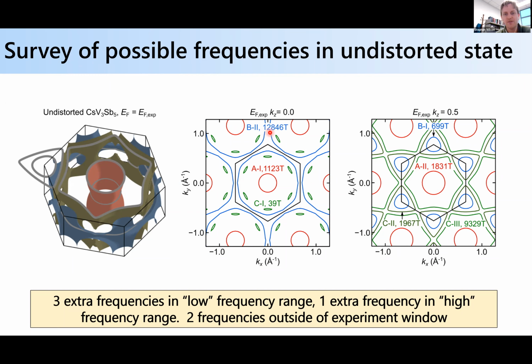first of all, just note that there are 2 frequencies that aren't within our experimental resolution. They're too large. But if we count all the remaining frequencies that should be within our experimental resolution, then our data sees 3 extra frequencies in the low frequency region and 1 extra frequency in what I call the high frequency region. So that's consistent. We expect that there should be some reconstruction of the Fermi surface as we cool below the CDW state, but this was just an initial check.